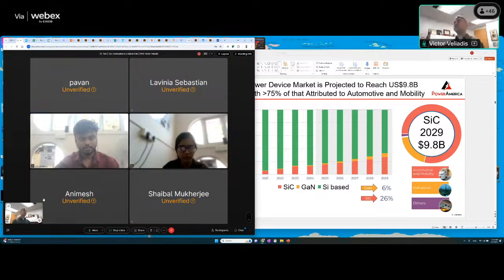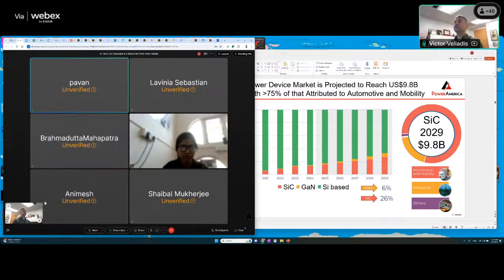So you have the trench MOSFET that's coming from ROHM and Infineon, and these are two giants, especially Infineon when it comes to silicon carbide devices. They're using trench in the case of Infineon because they have a platform that makes trench, easy to make. And even when you get to 3.3 kV and beyond, where the trench is not really helping you, because remember the reason behind the trench is to reduce the channel resistance, right? Because you have vertical conduction with higher mobility, and because it's vertical, the size of the device becomes smaller.